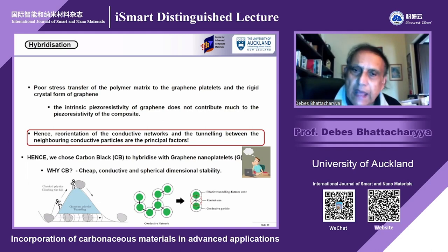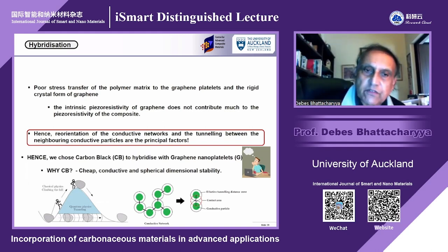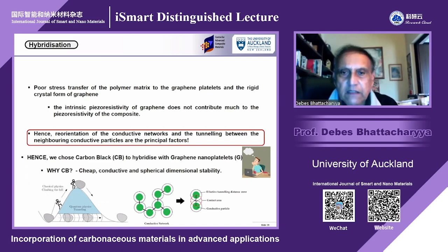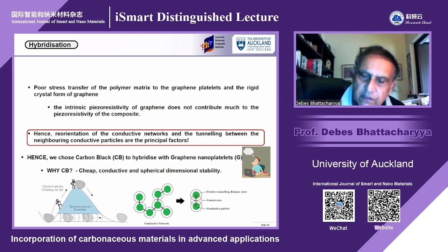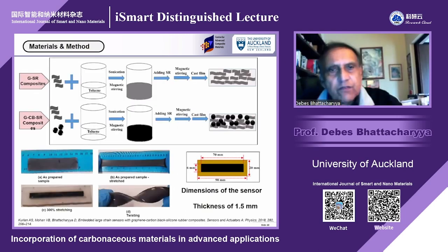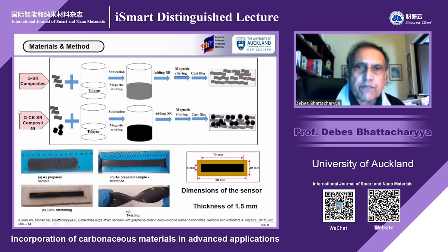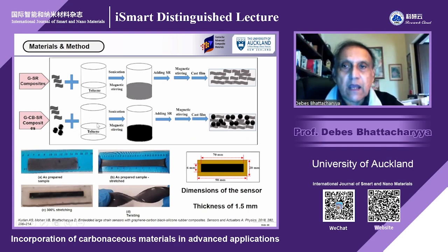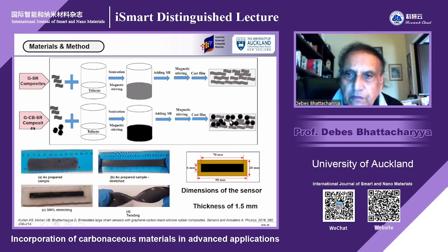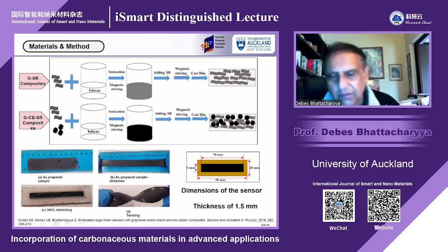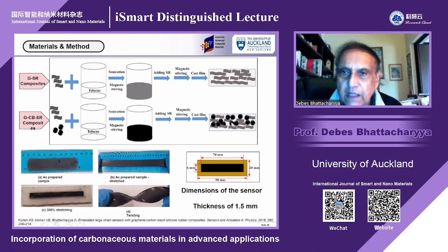We chose carbon black to hybridize with graphene nanoplatelets. Why carbon black? It is cheap, conductive, and has spherical dimensional stability. Forget about the manufacturing part, it is very similar: you dissolve, and then you add carbon black. Instead of having only the cast film of graphene platelets like that, we are putting in some carbon black. This spherical carbon black may not be comparable dimensionally, but it goes inside and makes some kind of connectivity.